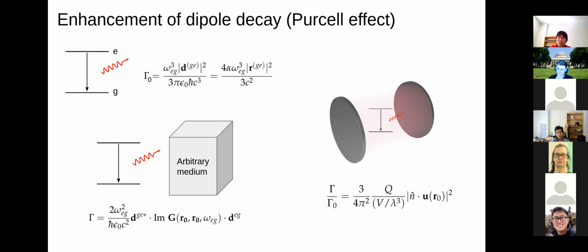Another thing I'll point out really quickly is that this n·u factor, which determines how the mode overlaps with n, which is like the dipole vector of the emitter, if you were able to fix it into a single direction. If you construct a situation where these things don't overlap, you can also suppress the spontaneous emission rate and create a situation where the lifetime of an atom, or of a transition in a quantum dot or something, ends up being much longer as a result of not being able to couple very well to any mode that's in its environment.